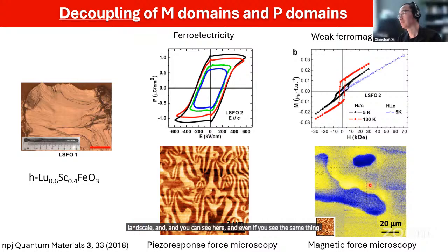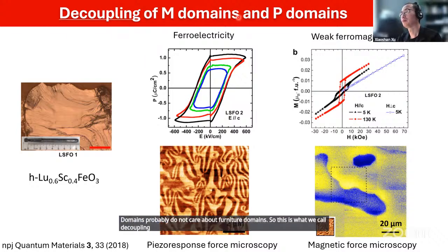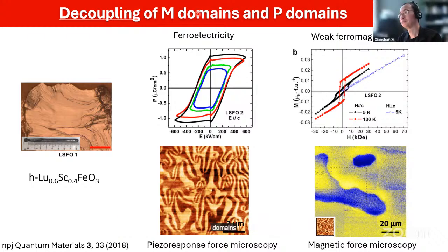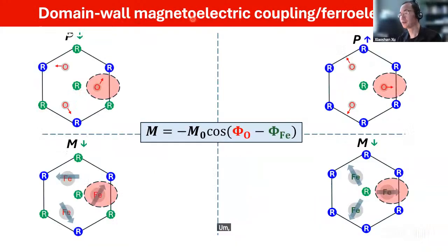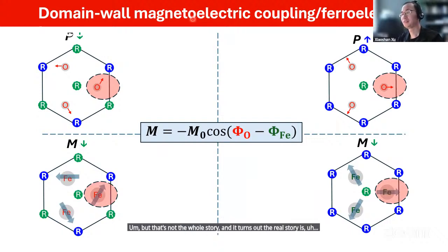The magnetic domains probably do not care about ferroelectric domains. So this is what we call decoupling of domains between magnetization and polarization. Okay. But that's not the whole story. It turns out the real story is actually more interesting than that.